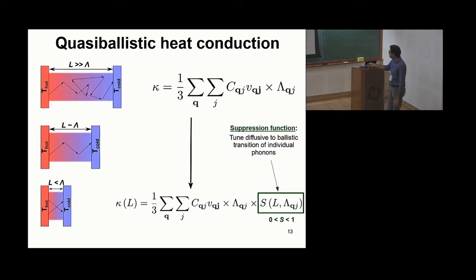So this quantity S tells you how much of the transport is happening in a diffusion manner and how much is happening in a ballistic manner. This function you can compute from the Boltzmann equation. When you solve the Boltzmann equation for this particular experiment, you get this kind of form for thermal conductivity. In the limit where all phonons transport heat in a diffusion manner, the S function is uniformly 1, in which case it just reduces to this equation.